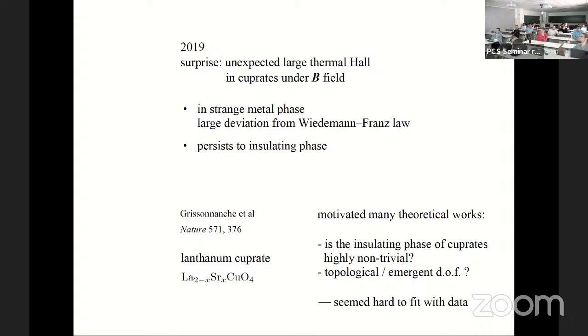So that means it has nothing to do with whether the strange metal satisfies the Wiedemann-Franz law. It's something more general in these materials themselves. That's a very easy way to violate the Wiedemann-Franz law: if the system has two types of quasi-particles, then, right. So it has nothing to do with the strange metal, really. But the original motivation was to look for that. That's why people started doing the experiment. But then they found even in the insulating case, it has that. So it's unrelated to the Wiedemann-Franz law.